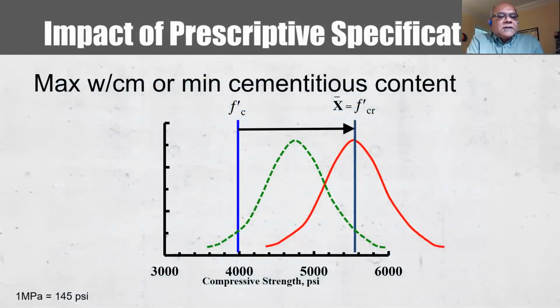One of the things that impacts the sustainability, if you will, of concrete is the actual average strength that is used in a submittal. And so you have f'c, which is the design strength used to design the members, but the concrete producer has to design for a little higher than the design strength, so that you have a very low probability of test results that are less than the design strength. Generally, what you see with prescriptive requirements, such as a maximum water cement ratio or a minimum cement content, is it drives the actual average strength to a much higher level than necessary for the general over-design requirements.